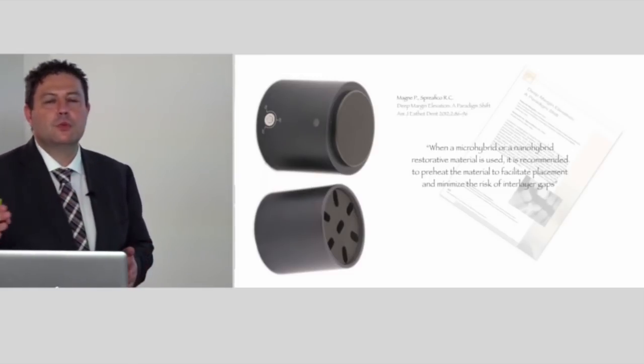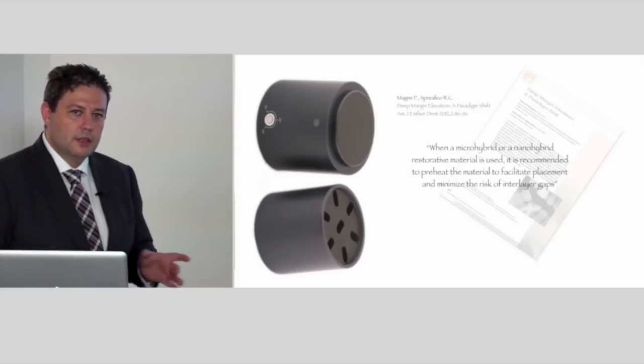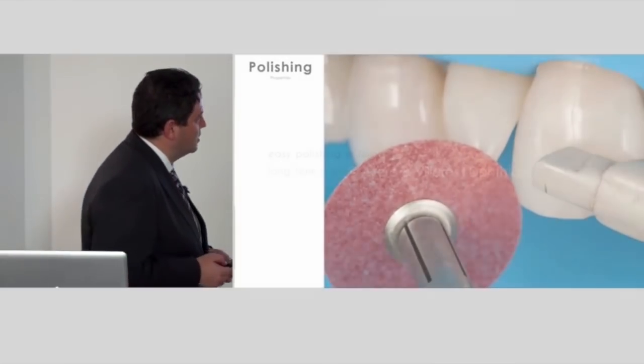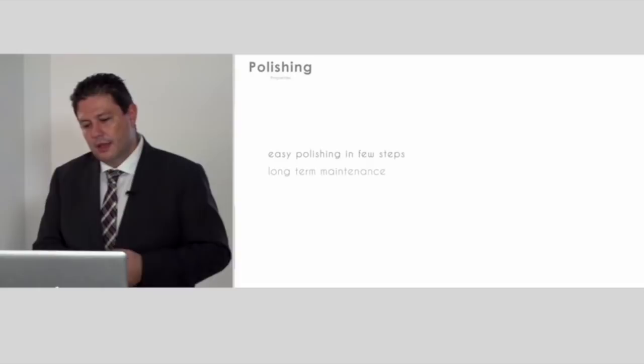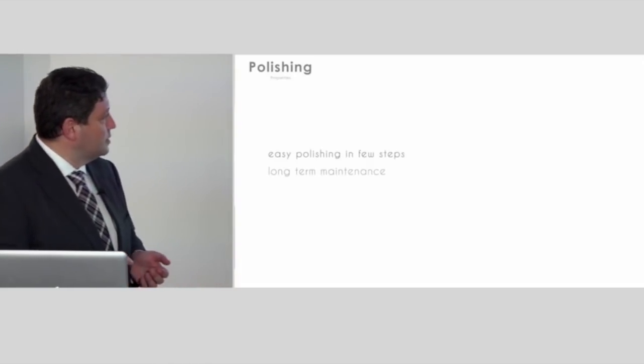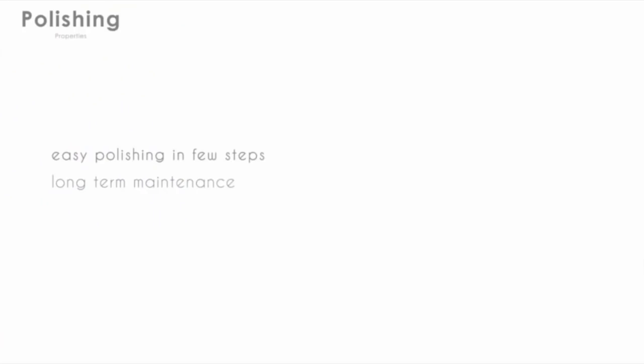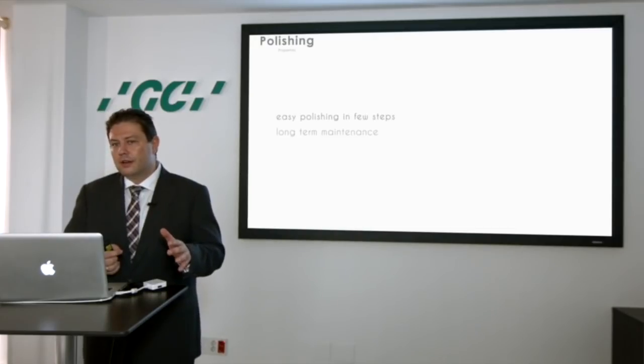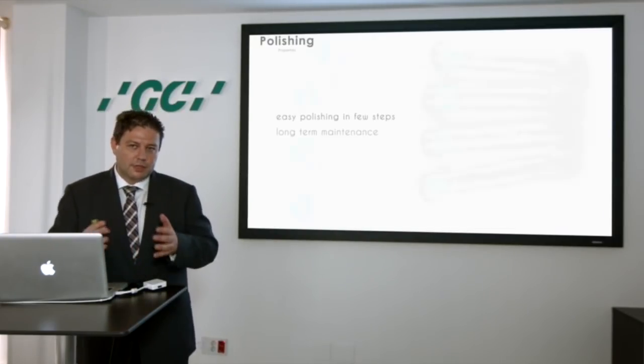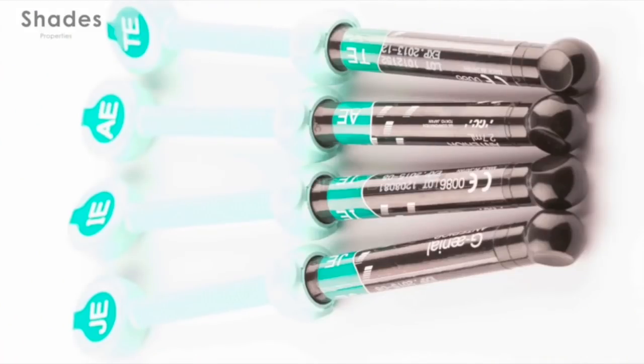So one of the properties that we want in our material is good handling. The second property is good polishing. That means in our practice, easy polishing, few steps, not so many steps to have a good shine, and if we can have only one step, it will be better. The other thing is long-term maintenance of this polish on our material. For sure, the gold standard in this material are the microfillers, but they are not strong enough, so we need to have a balance between microfillers and the new materials.